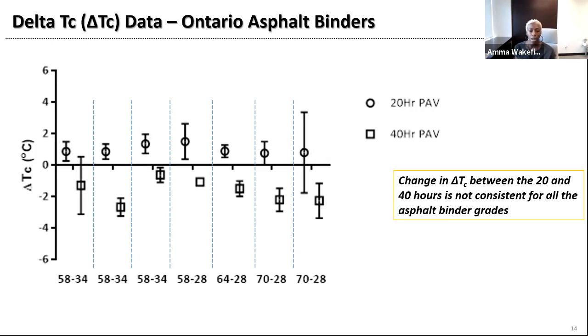This is giving producers and also agencies an idea of where we currently sit in terms of the delta TC value for the binders used in Ontario. And it is source specific, but you can see the range in the values for the different asphalt binders. You can also see the difference in 40-hour and 20-hour PAV, but it's interesting to note that the difference in 20 hours versus 40 hours is not the same for all of the binders. And so this is a very important chart to show also that when you're talking about delta TC, the condition or the aging is a very, very important thing to include before we start looking at limits and what the delta TC value means. So be sure to know if you're looking at 20-hour or 40 hours.